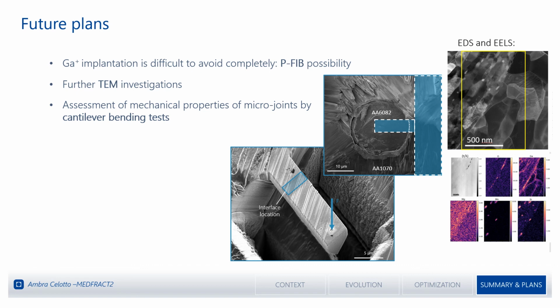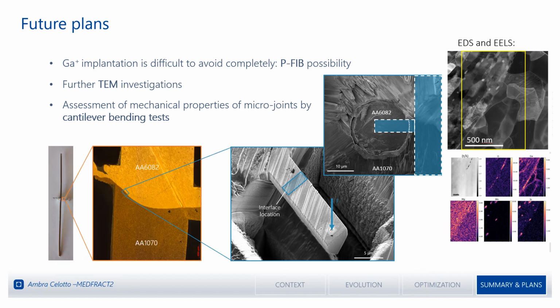The cantilever is meant to be created by putting the interface region really close to the root of the cantilever in order to create a tensile stress condition on the interface and to try to test it in a tensile mode. And this will be first done on a macroscopic sample, what they call a pressure welded joint, both to act as a trial, but also as a reference for the microscopic one.